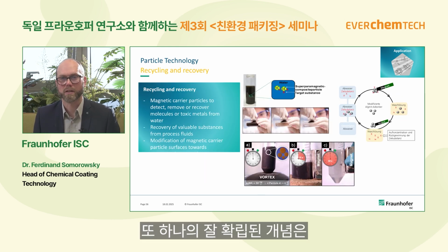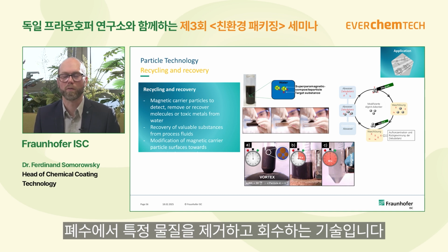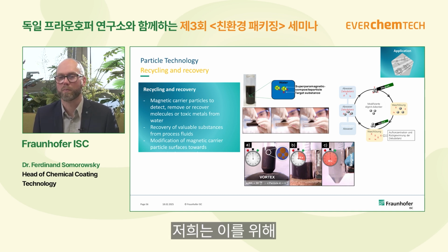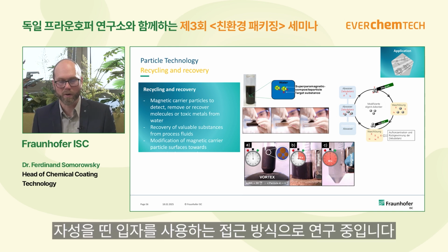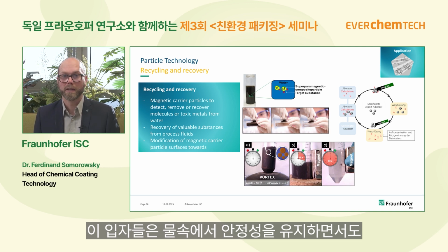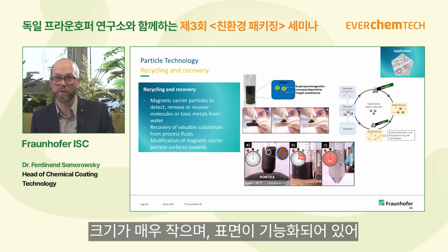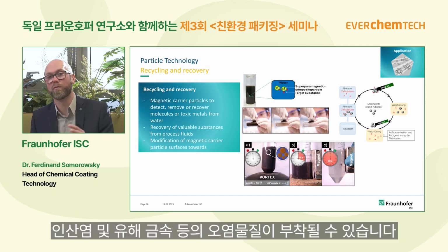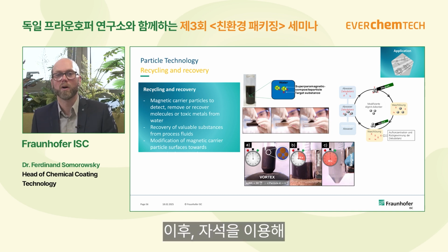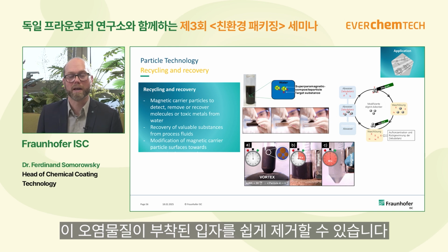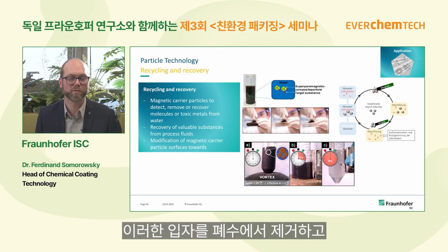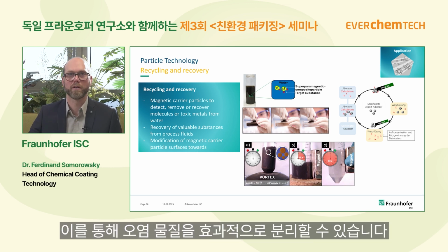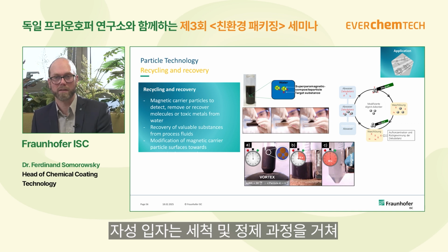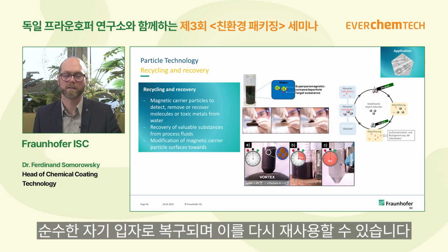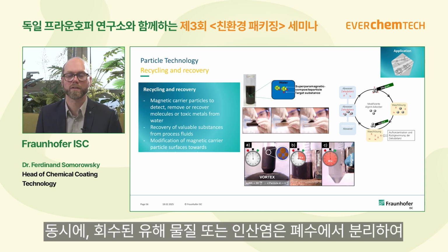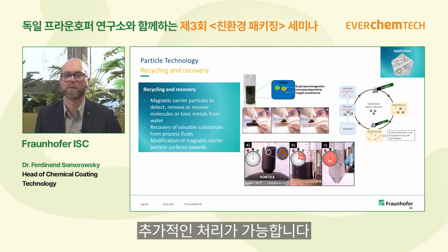A well-established idea is the removing and recovering of materials out of wastewater, and we have the approach to use magnetic particles. These magnetic particles act like a carrier, so they are stable in the water because they are very, very small, but the surface is modified, and for example phosphates and toxic metals can adhere on this functionalized surface. Then by a magnet you can remove these particles from the wastewater and clean it, and then you can recover the magnetic particles. Then you have the magnetic particles again as a pure material and can reuse them, and on the other side you have these recovered toxic materials or phosphate from the wastewater.